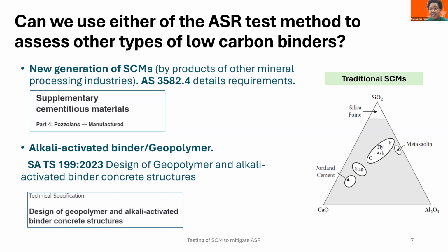So we have a standard that actually allows us towards the use of manufactured pozzolan. Well, the key term here is still a pozzolan, which means we're still not allowed to just chuck in anything in the concrete. So you just can't replace cement with anything. So there are still guidelines. You still need a level of fineness, a level of alkali concentration, a level of SCM chemistry that you have to meet to be able to first be used in the concrete.